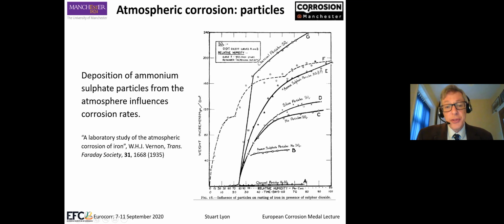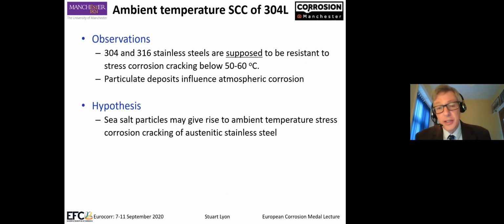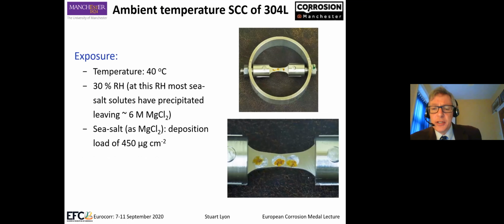So you then have the hypothesis that since ammonium sulfate isn't present in the atmosphere anymore, perhaps it's sea salt particles that give rise to this ambient temperature stress corrosion cracking of austenitic stainless steel, because it's well known that particulate deposits can influence atmospheric corrosion. So we did this small tensile experiment using a proving ring with this wishbone sample, bow tie sample. And at 40 degrees centigrade, although we've run these experiments down to about 20 degrees centigrade, the initiation time for cracking just takes longer and longer.